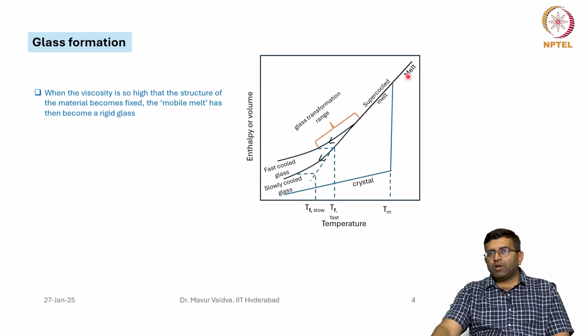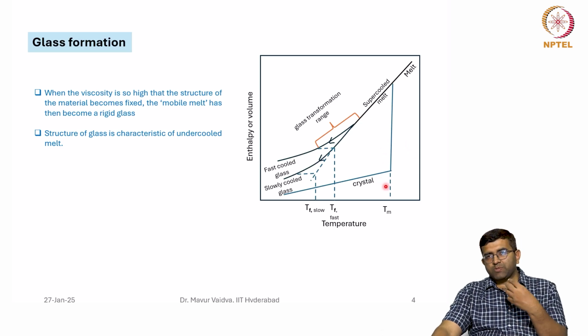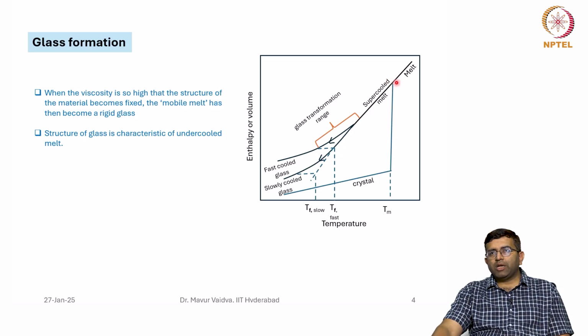So, if the liquid is brought below the melting point, then it will try to convert to the crystal, and that will lead to a decrease in the volume or the enthalpy. However, the crystallization proceeds by nucleation and growth, which requires time. At the melting point, the structure of the melt is a disordered structure. When it becomes crystalline, it attains a periodicity and a certain order. So, this requires a nucleation and growth process which needs time.